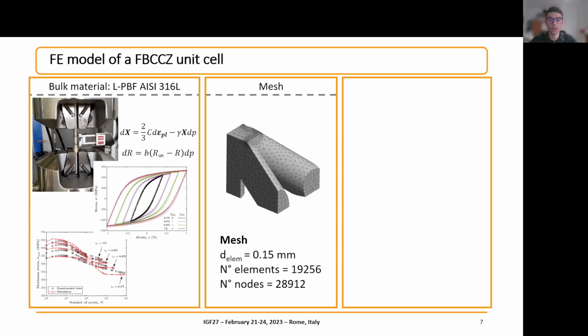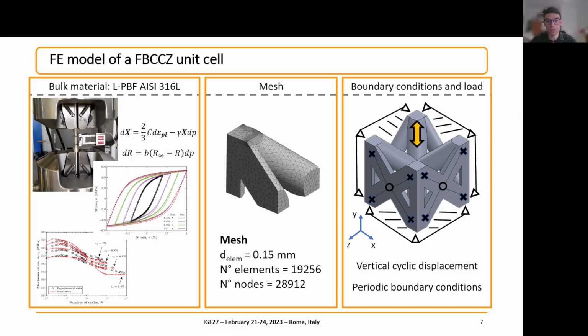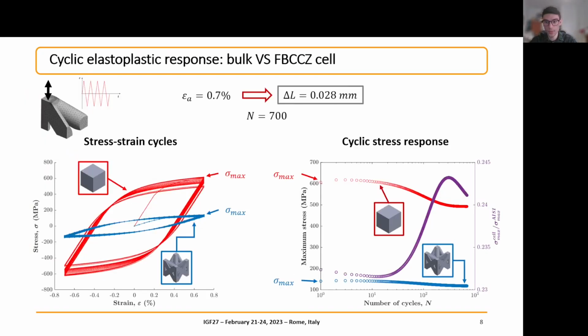Actually, we simulated the response of only 1/8 of the cell to reduce the computational cost, since one of our goals is to find a fast and accurate way to model the cyclic behavior up to the stabilized state, which is computationally demanding. Then, of course, we imposed a cyclic displacement and used periodic boundary conditions. Here, as an example, I present a comparison between the simulated response of the bulk material and the unit cell for an imposed macroscopic strain of 0.7% for 700 cycles. Without going into detail, both the stress strain cycles and the cyclic stress response showed that the unit cell has a similar cyclic behavior compared to the bulk material, with some small variations.